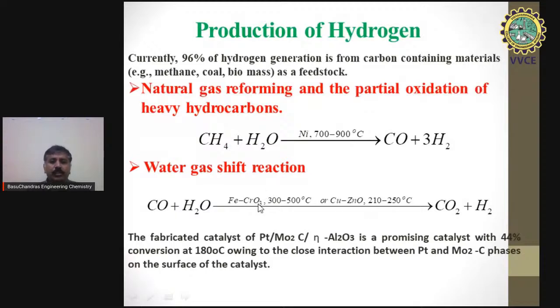These are the catalysts which are commonly used for the water gas shift reaction: iron chromic oxide catalyst and copper zinc oxide catalyst. This particular catalyst works at lower temperature when compared to the other one. And newly, they have discovered one particular catalyst, platinum molybdenum carbide, which is doped on aluminum oxide. This catalyst has higher efficiency compared to these two catalysts, with 44% conversion efficiency, and it works even at a lower temperature of 180 degrees centigrade. And in future, this particular catalyst will be used in the water gas shift reaction.